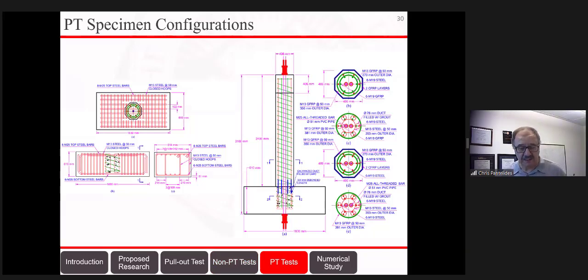So now I move into the next phase, which is the post-tensioning columns. These were the two tests that we did in addition to the previous two, where everything was the same as far as the longitudinal bars. The hybrid had a combination of 6 steel bars and 6 fiberglass, and the all-steel had 12 steel bars. But now the new element is, of course, the addition of the two 1-inch threaded high-strength steel bars. These bars have a yield strength of about 120 KSI and an ultimate strength of 150 KSI.